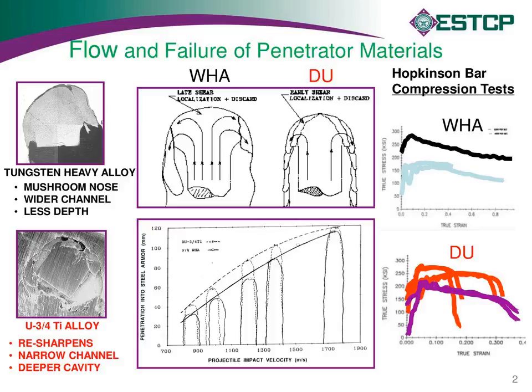At the bottom center, I show a comparison of the penetration tunnels being made by equal mass, equal density, equal dimension DU and tungsten penetrators. So they both have a density of 18.6 grams per cc. And if you can see, the DU penetration tunnel is narrower but deeper, and that difference is especially obvious at the lower velocities, but it continues and basically reasserts itself later in the process at the higher velocities. The cartoon immediately above that sort of shows the illustration of what's happening.